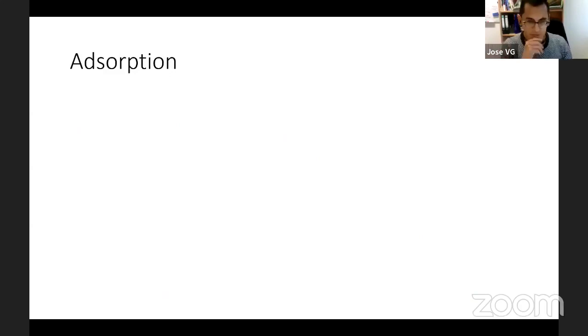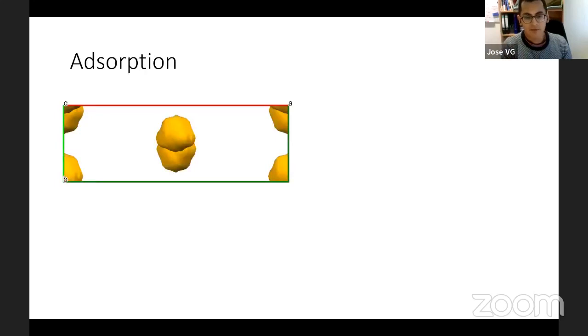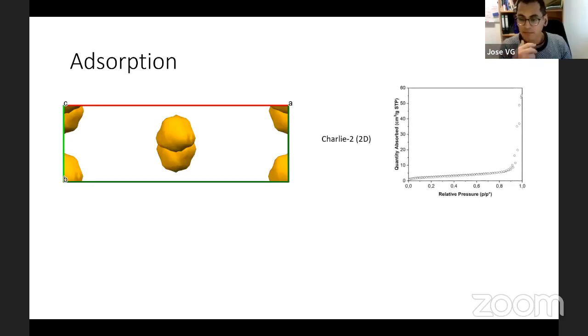We have checked the adsorption of this material. We have seen that in Charlie 2, it has some pores. However, the pores don't have the possibility to be connected or to escape. So practically the pores are useless. There is no possibility to encapsulate something inside of the pore, or to introduce or take out something from inside of the pore. And we see that in the adsorption graph. We have made some adsorption measurements, and we don't see really important adsorption in the material.